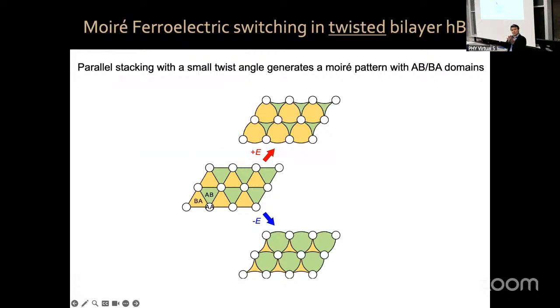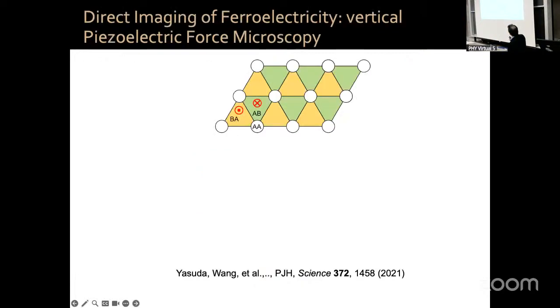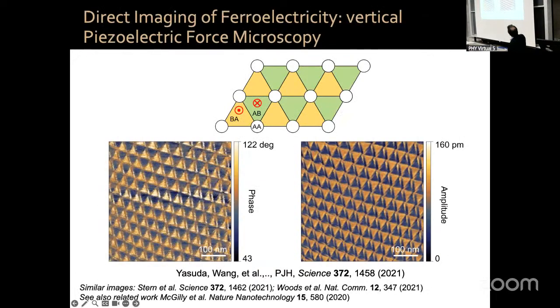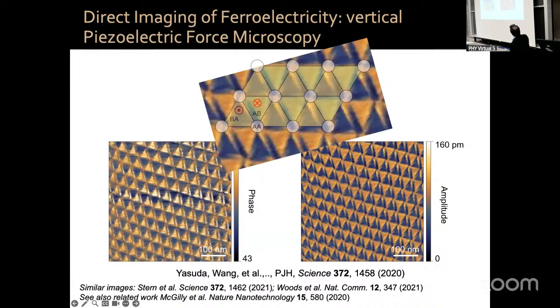If you twist a little bit, now you form the type of AB/BA domain that you have in magic angle twisted bilayer graphene, except that now they are different. They have opposite electric dipole moments in this Moire pattern. So can we see this actually? Indeed, if you do piezoelectric force microscopy, which measures the polarization, you can see these patterns in the phase and amplitude, where you see these Moire patterns with opposite electric field, alternating these Moire structures. You can put it on top of each other like that.